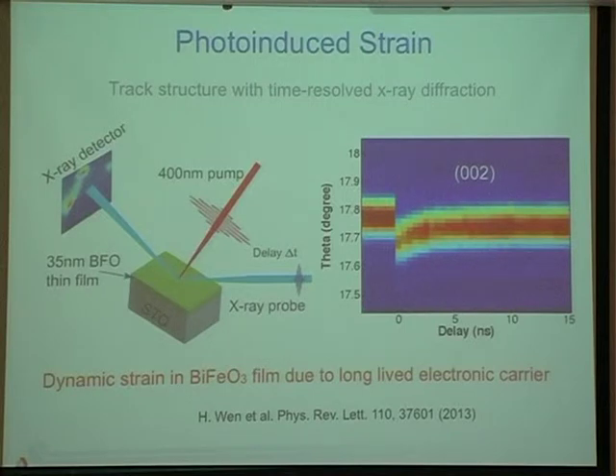And so what we found is we could generate an ultra-fast lattice expansion. And this is almost like you're tying a string to this material and pulling on it. And so here I'm showing you what the lattice structure is doing. It turned out with bismuth ferrite, the electronic properties didn't really change much. But in a material that was very sensitive to the lattice expansion, you could do a dynamical experiment where you could try to drive it in new ways and see what would emerge.